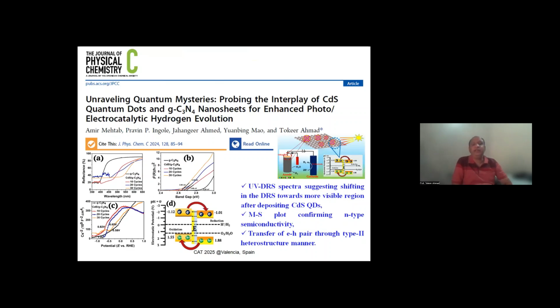Now coming to another binary heterostructure. In the previous slide, the band structure mechanism belongs to the Z scheme. Here, cadmium sulfide quantum dots are grown on the graphite carbon nitride with the help of the SILAR cycle, and the charge transfer dynamics suggests type 2 heterostructure formation for this cadmium sulfide with graphite carbon nitride heterostructure, and we have reported efficient photo and electrochemical hydrogen production.